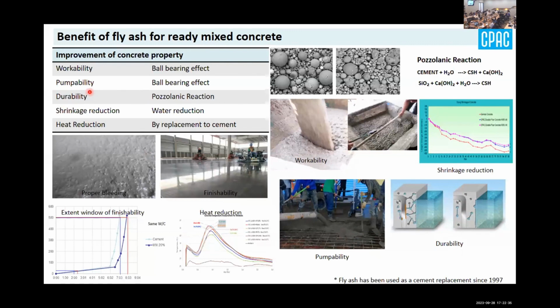The next one is about the durability, because fly ash gives a pozzolanic reaction and gives more dense concrete in the future, with less strength loss. So this one is also really important for some kind of severe environment. When we use fly ash in the concrete, you can reduce the water content, so you can reduce the shrinkage. Talking about the drying shrinkage in the concrete, this is one thing that we always consider for floor type and large area casting. It's really helpful for this.